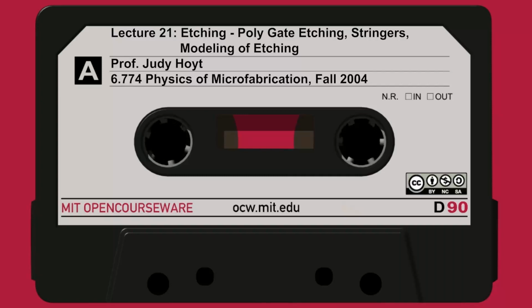What's the other bad thing? Well, your over etch may not be perfectly anisotropic. It may be etching sideways a little bit on the gate. So unless it's perfectly anisotropic, you'll have that. So there's always a balance with over etch.